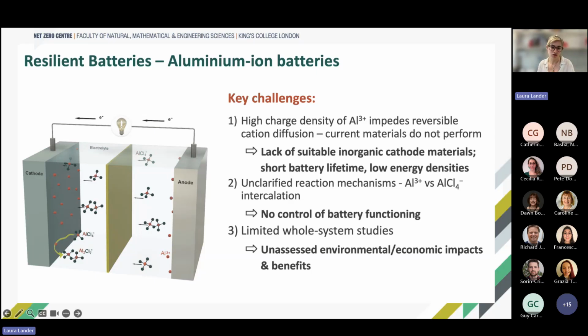So whilst the functioning of aluminium-ion batteries has been proven already in literature in the past, there's still a lot of key challenges. One of the biggest differences between aluminium-ion batteries and lithium-ion batteries is that instead of lithium, we cycle aluminium, so aluminium 3+. But since aluminium 3+ has a very high charge density, meaning a charge of 3 on a small radius, it has a lot of strong electrostatic interactions with our inorganic cathode materials, for example, the oxygen or the transition metal oxygen framework.